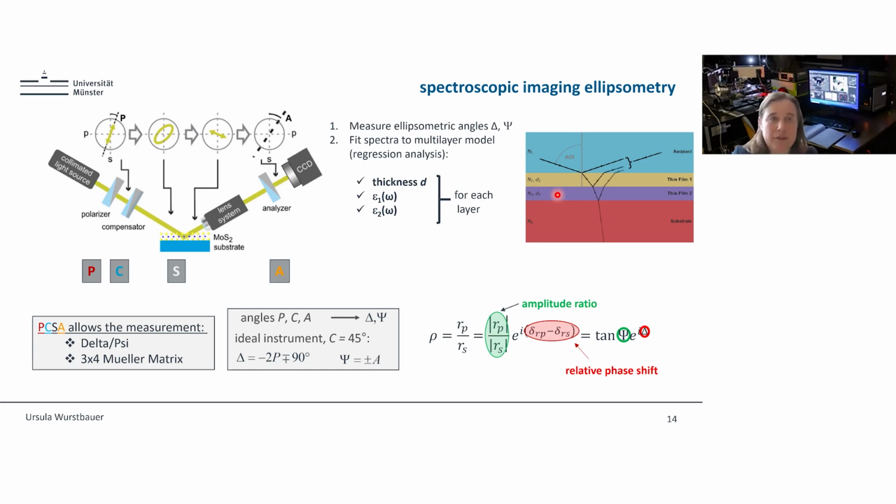However, typically we don't do it in-house because we don't have a rotation stage connected to the cryostat. The Mueller matrix approach is required particularly if we have an anisotropic material or depolarizing effects. Then we have to switch from the Jones matrix to the Stokes formalism, and the Mueller matrix is required.